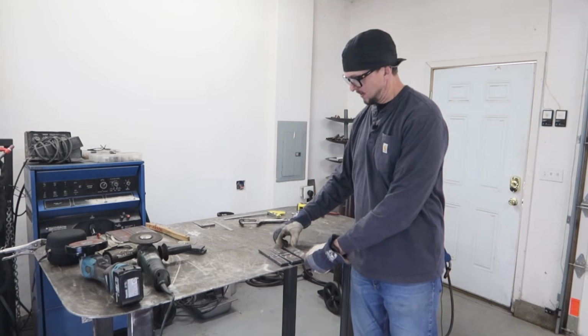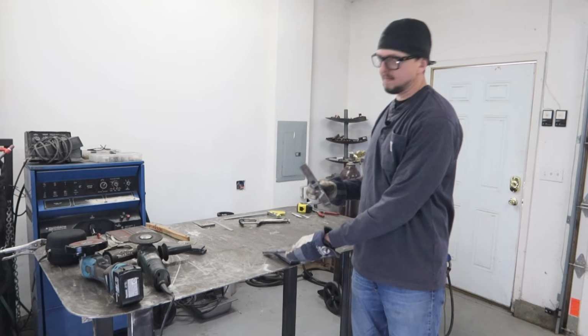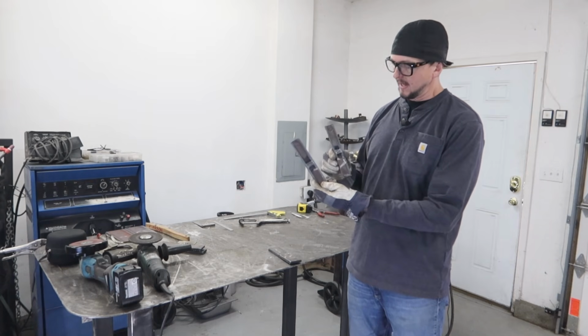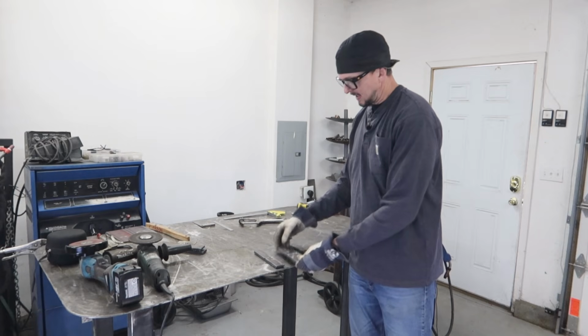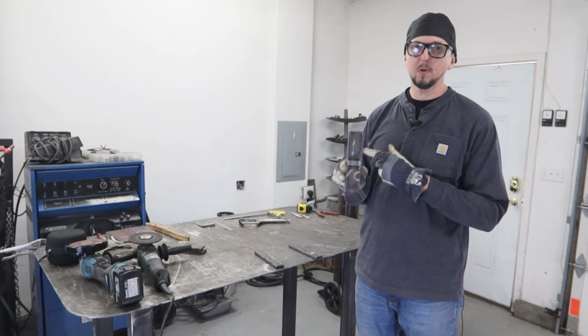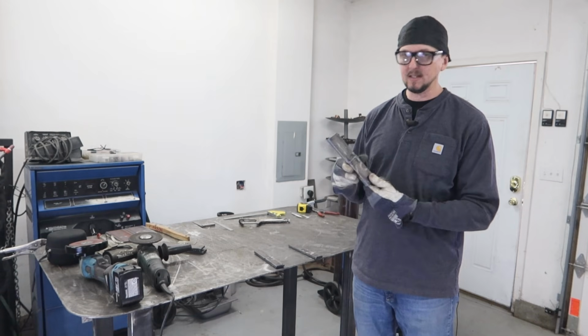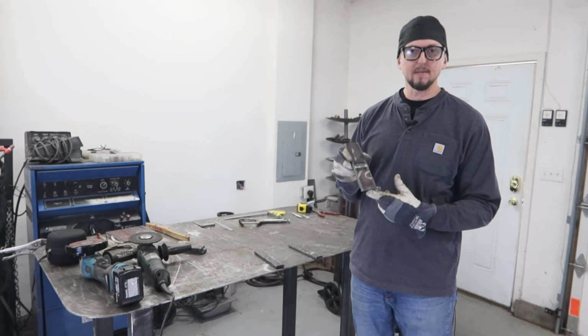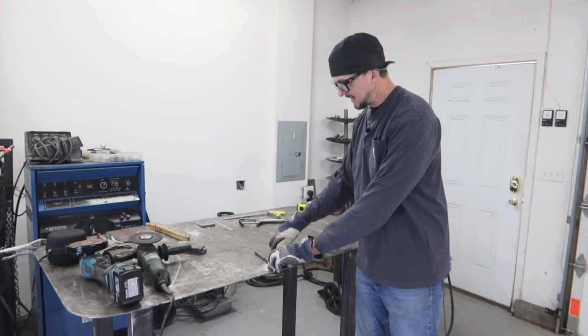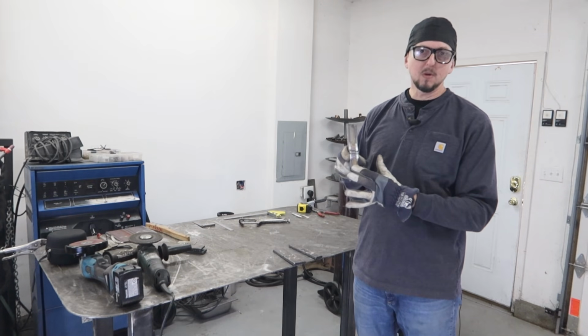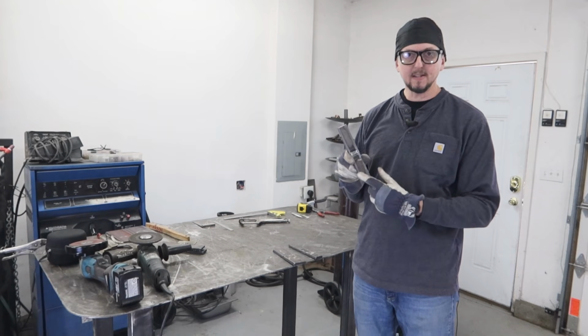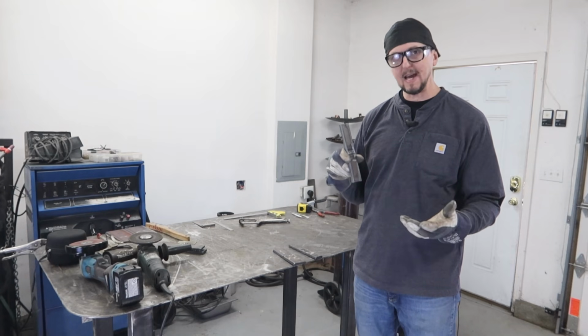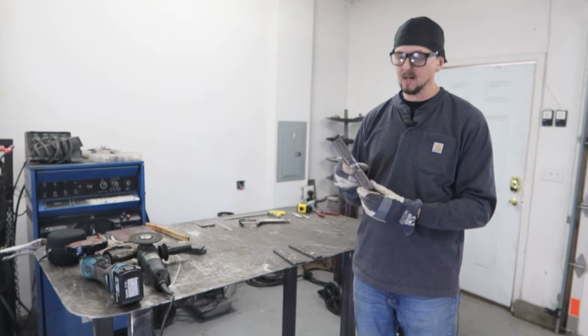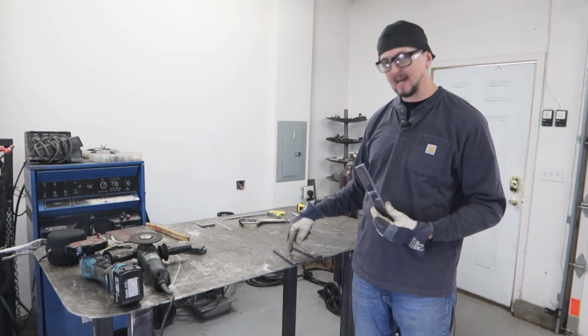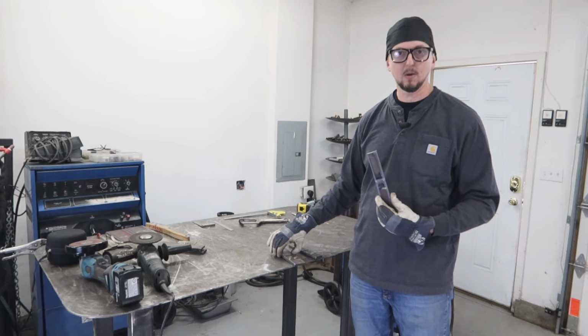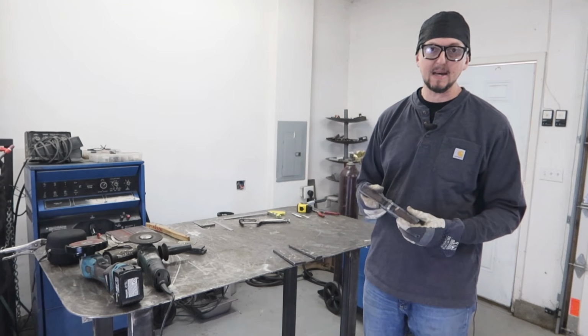And that leaves us with our 2 bend specimens, one for face and one for root, and then a 2-inch center section. So we want to hold on to this 2-inch center section because the D1.1 code says that if you have a corner crack coming from the corner of the bend test that exceeds 1/4 inch and it's not from visible slag inclusion or fusion type discontinuity, you can actually retest from the center section. So it's a good idea to hold on to that until you're sure that you've passed the test.